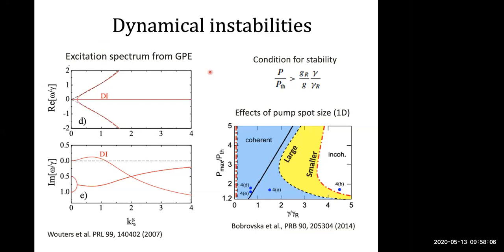So what was predicted theoretically is that in addition to these sound-like excitations in the condensate, you also have the presence of a dynamic instability, which is due to the reservoir. Why is it unstable? This is a mode or an excitation with an imaginary part which is positive, so an excitation which grows in time. There's a condition for the presence of this instability, which is almost always satisfied for typical organic polariton lasers. So we expect this instability to be present.